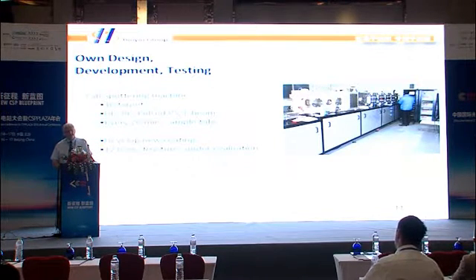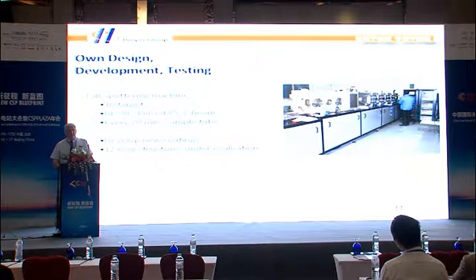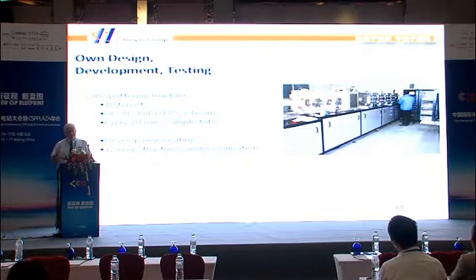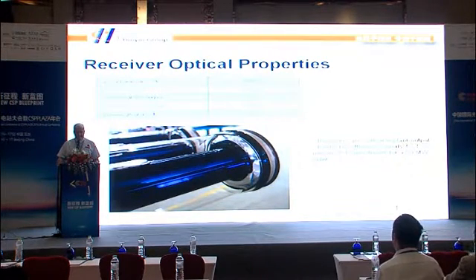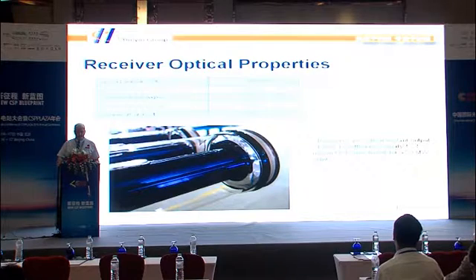With that we have been working, and we have been able to improve the stability of the selective surfaces a lot. Currently we have 12 selective surfaces under evaluation, where we are looking at which are the better ones at a certain given temperature. The current receiver that we have in the market has an absorption of 95.9, thermal emittance at 400 degrees of 7.8, transmission of the glass of 69.9 and a length of 79.8. So it is one of the better receivers on the market.